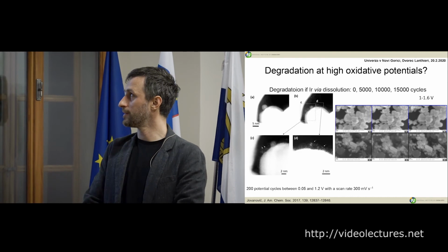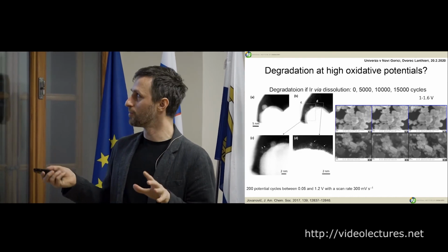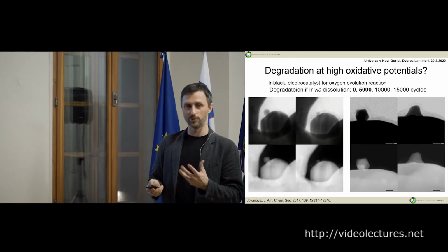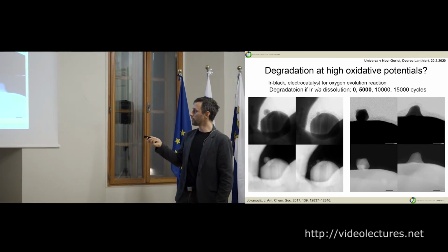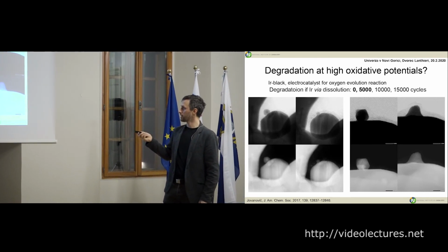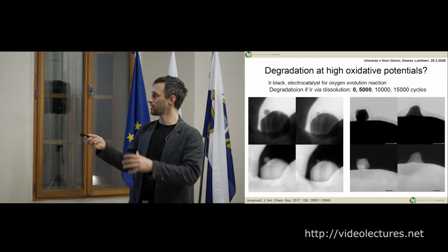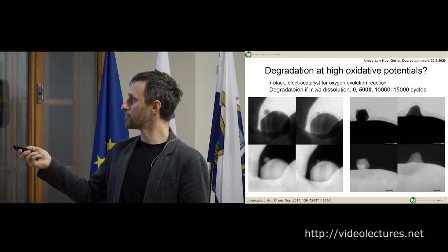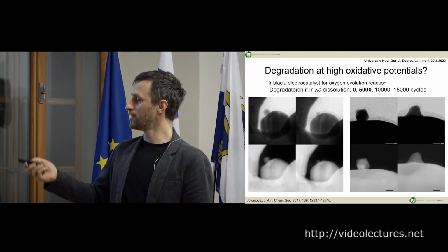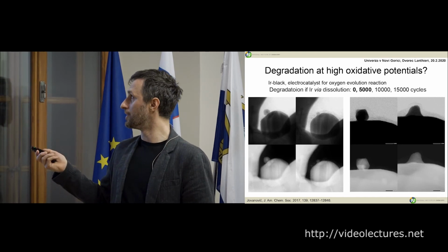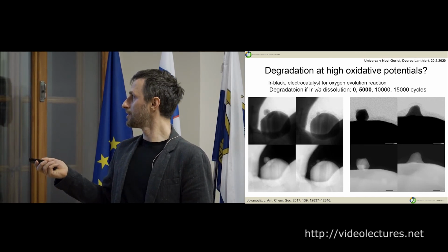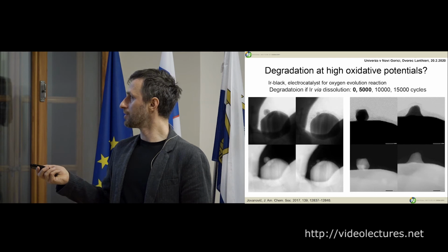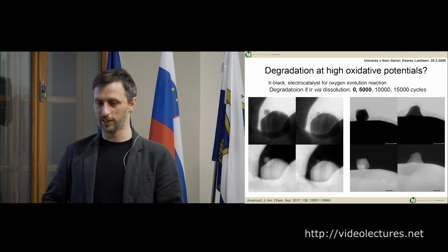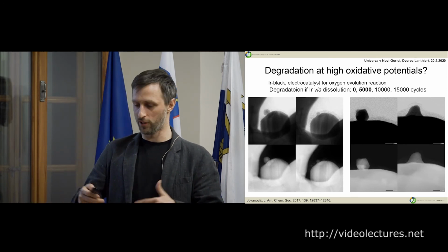Now here is identical location, and this is one of the rare locations where we saw some effect. If you look at these extra nanoparticles on these surfaces, you can see that they change. And this is the change that occurs. What's happening here, we say that iridium is oxidizing, and then we're reducing it.